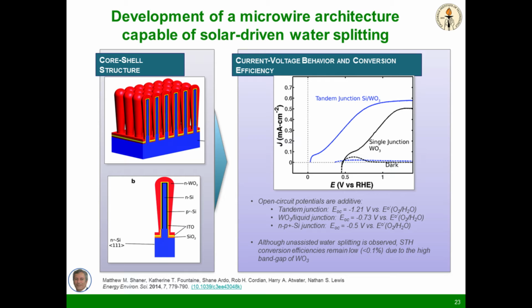And so we believed that we could piece together a system which would actually be the first implementation successfully of this membrane-bound water-splitting device. We did that. We published it. This device does work, but it's not very efficient, and we knew it wouldn't be efficient because the electronic band properties of tungsten oxide are misaligned with respect to optimal performance of the electrons with silicon, and for the aficionados, the band edge positions are not negative enough on tungsten oxide to actually support the efficient unassisted array along with its band gap. I'll tell you a little more how we've changed that scene with stabilizing entire classes of materials for this purpose later on.